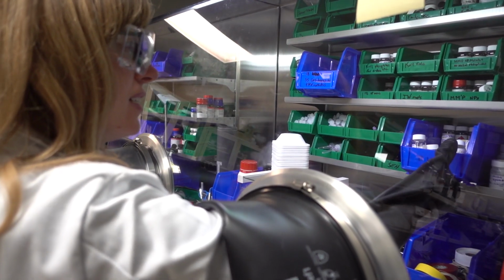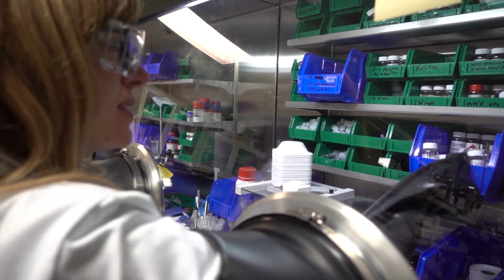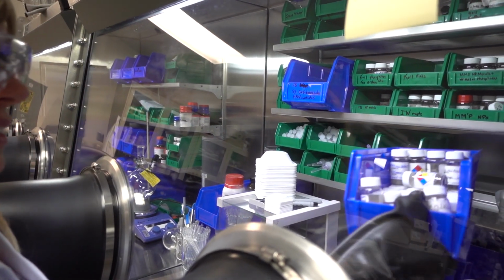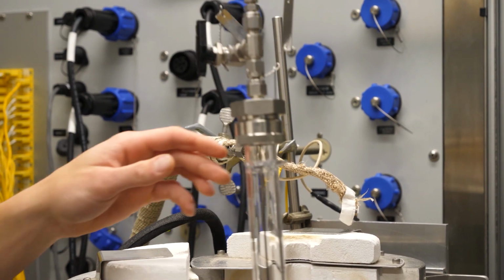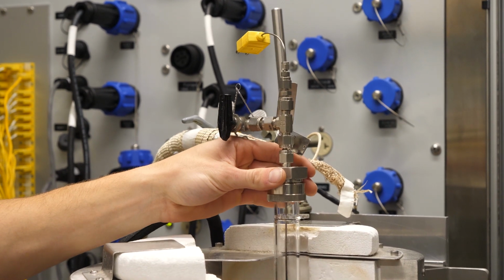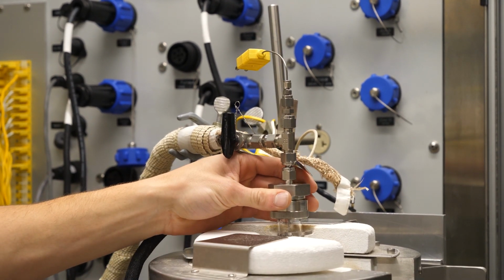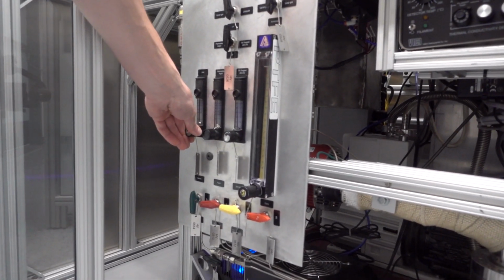We commonly make metal carbide catalysts by starting with a metal oxide precursor and heating it up in the presence of a reactive carbon source. We most often use a methane-hydrogen mixture and then heat it up to temperatures as high as 590 degrees for an extended time.